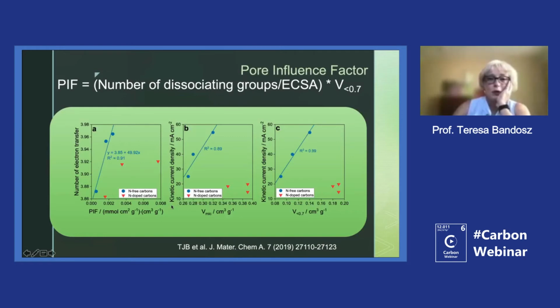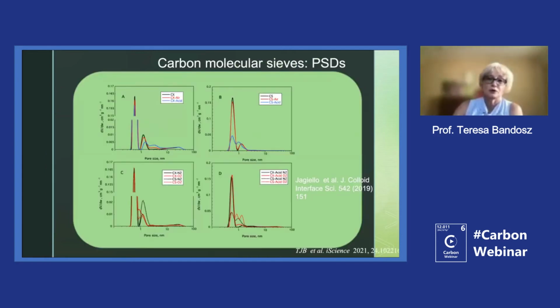And then we look at the kinetic current density and at the volume of those micropores and the volume of the pores smaller than 0.7 nanometer. And so there is a dependence for the small pores. Apparently, as I mentioned, in the case of the carbons which were modified with nitrogen, the distributions were the same, so we didn't see the effect, and the distribution of the points is likely related to a different mechanism on those carbons.